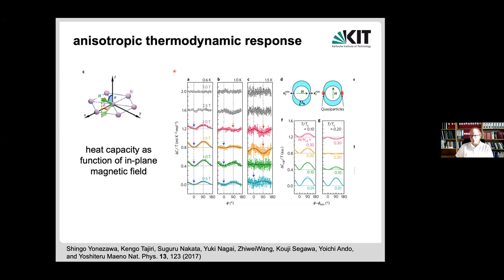My suspicion is you have a certain direction in which you essentially have an amplitude of the order parameter set. It's just still phase fluctuating. That's what's happening, right? I'm talking about how you pick it up in the experiment, right? How the superconducting conductivity, as Peter Armitage showed, hangs together with the order parameter. What you have to do, again in the nematic phase, and only there can you make a symmetry statement, is measure sigma xx and sigma yy, take the imaginary part and look at the one over omega contribution. It has to be different. Yeah. But the question is, how large is the difference, given that your order parameter is this and that, right? Can you predict what the superfluid density would do in the different directions?